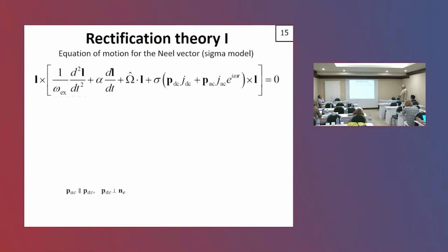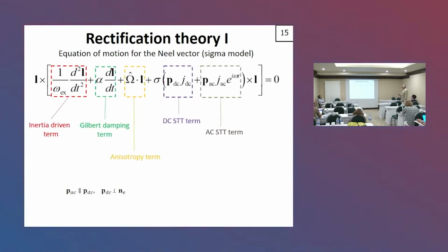I will not discuss these equations in detail. I will simply say that this is the equation for the Néel vector or order parameter of the antiferromagnet, which is basically the difference between the magnetizations of the sublattices. This term is the inertial term, where this is the effective mass. This is a damping term. This is the term describing the anisotropy of the material, and we will have two spin torque terms, one related to the DC current which we are supplying to move the frequency, and the AC current, which is our actual signal.